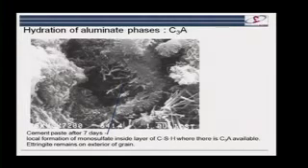complex, because the phases that form will depend on the local conditions. So again, you read in the textbooks, all the ettringite disappears and we form monosulfate. And then you can see this micrograph, and in this micrograph you can see monosulfate here. These little plates here are monosulfate, and this is ettringite here. Okay, so you've got the same sample, a few microns apart, with ettringite here and monosulfate here. So the point is it depends on the local conditions.